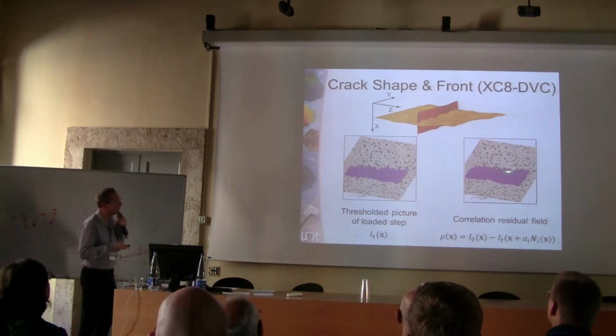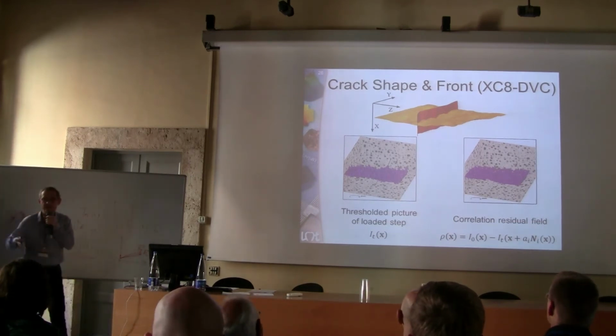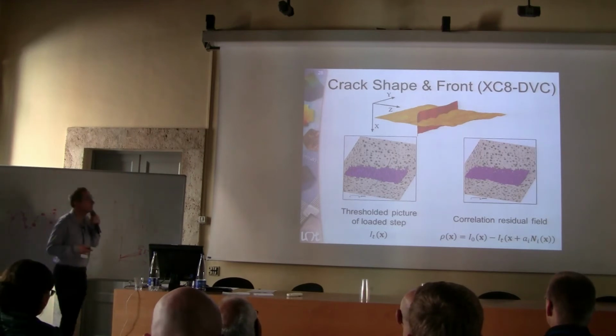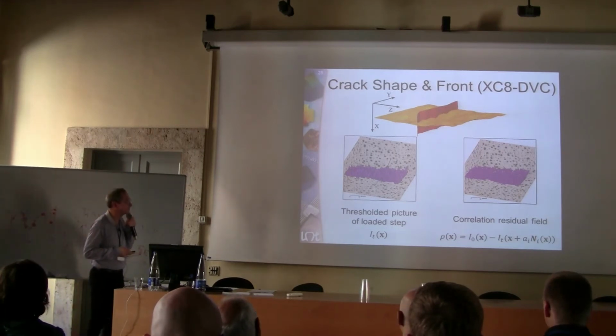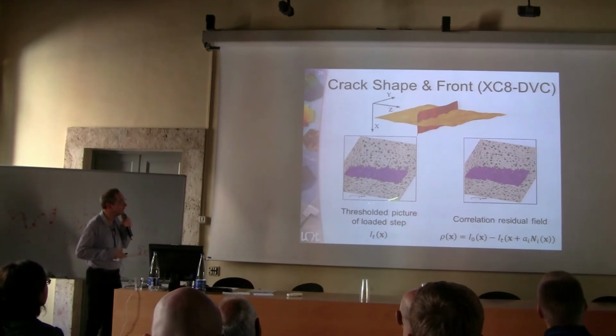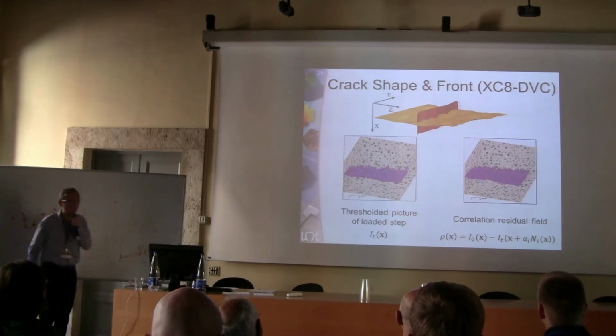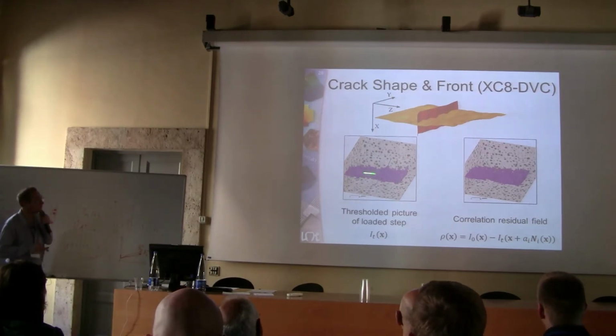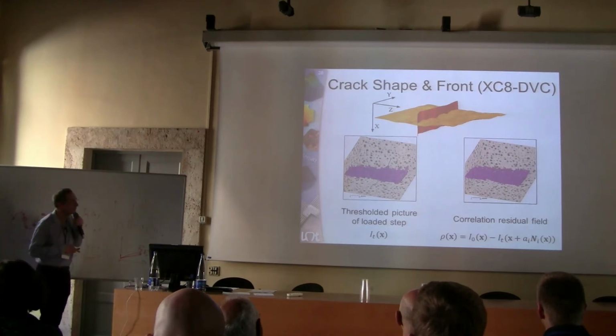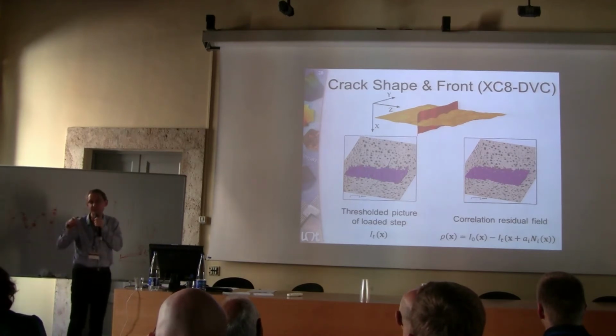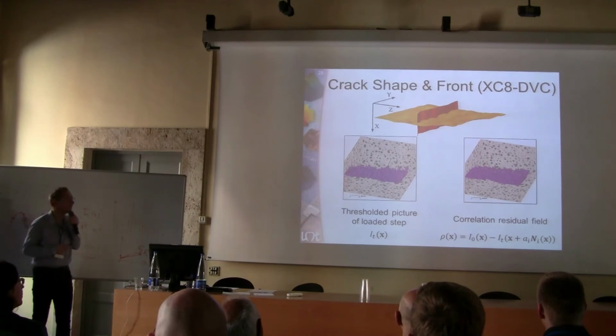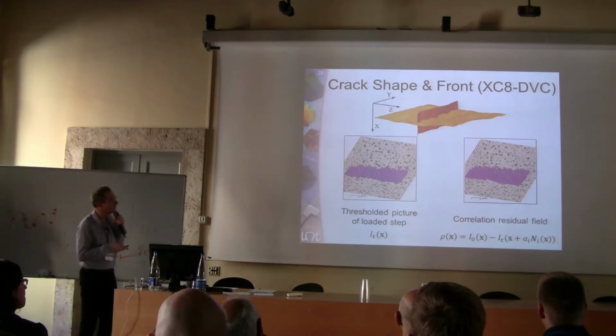This means that thanks to these residuals, you can construct the cracked surface and actually even use level set techniques that are used in extended finite elements. In this particular case, if you had just thresholded your picture, it would have been impossible to distinguish the cracked surface from the nodules, because in terms of gray levels, they were approximately the same magnitude.